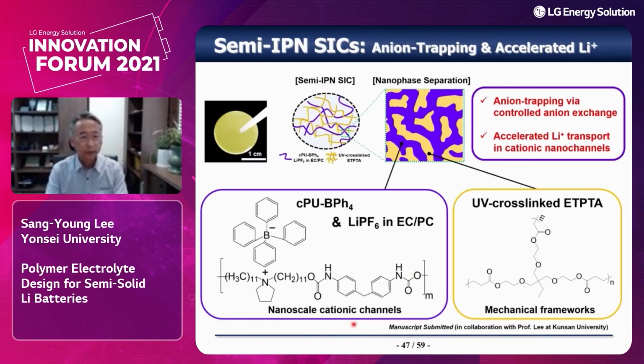Okay, and then we have further extended our concept to further improve the anion trapping effect. So here we suggest semi-IPN technology. Here the purple color represents our cationic polymer-based channels, and inside this channel, the cationic polymers are coupled with bulky anions, and the conventional liquid electrolyte was integrated inside this channel. And the yellow line represents the UV cross-linked triacrylated polymer network, which was used to act as a mechanical framework. Anyway, to achieve a solid-state electrolyte, we have incorporated the UV cross-linked ETPTA.